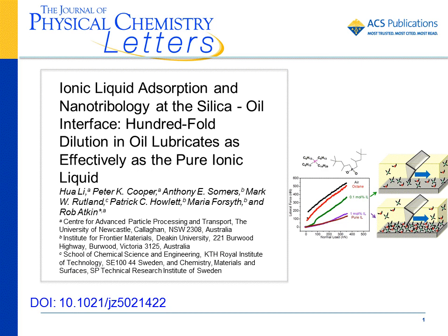I'm going to talk about our letter titled Ionic Liquid Adsorption and Nanotribology at the Silica-Oil Interface. A 100-fold dilution in oil lubricates as effectively as the pure ionic liquid.